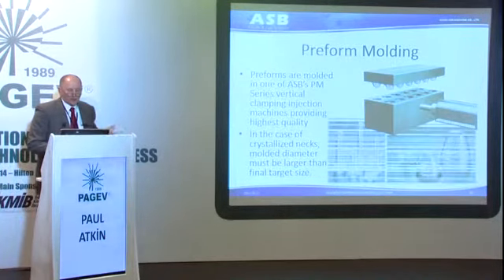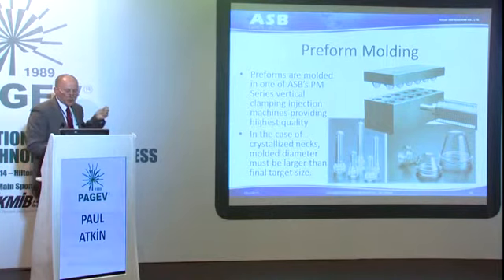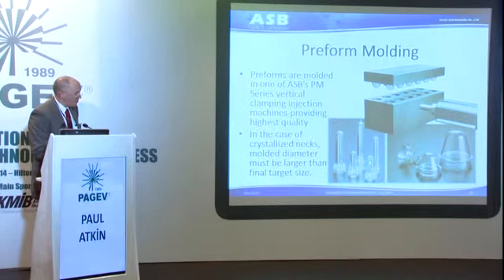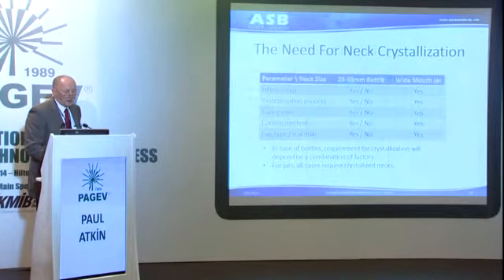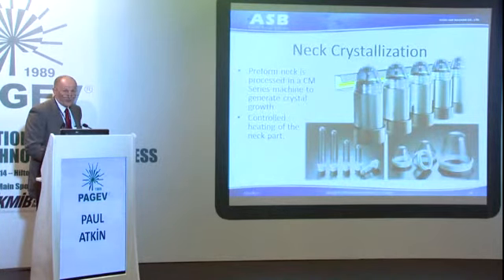So the process is very simple. We're going to use a preform molding machine to mold the preform initially. In the case of crystallized necks, the neck of the preform needs to be slightly larger because it's going to shrink. Or in the case of non-crystallized necks, the neck needs to be modified.